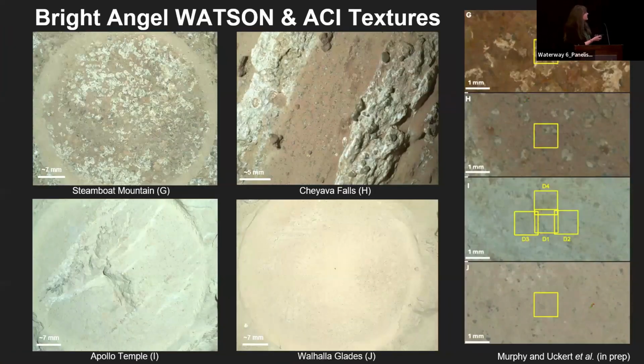If we take a look at our Watsons here, these 4 larger images, we can see that these are predominantly fine-grained mudstones. Some of the grains are so fine that they're below our resolution for our imagers. We do see these coarser grained olivines in Steamboat Mountain up in the corner, set in a finer grain matrix. And for the natural surface Cheyava Falls, there are these really coarse grained veins cutting through it. And even after we abrade it in Apollo Temple, we can still see those veins. The panel on the side are colorized ACIs, and those yellow boxes mark where we placed Sherlock. And each of those 1-by-1 detail scans that we performed, there's 100 points analyzed in each.